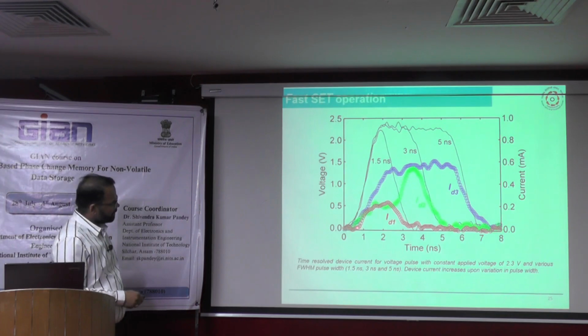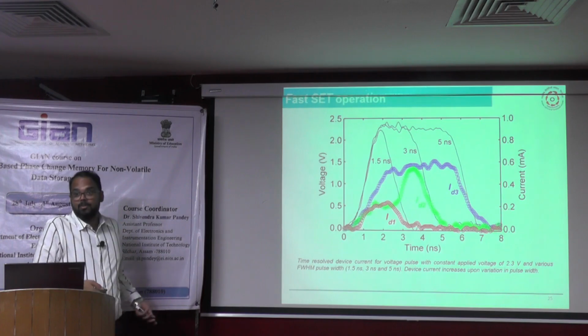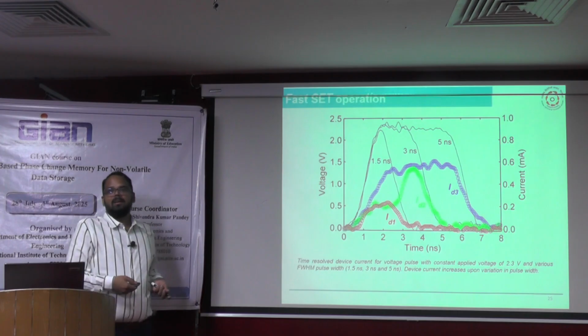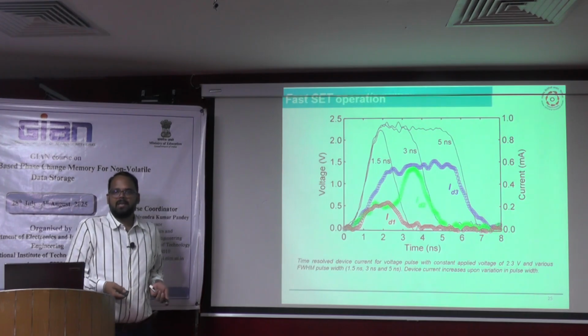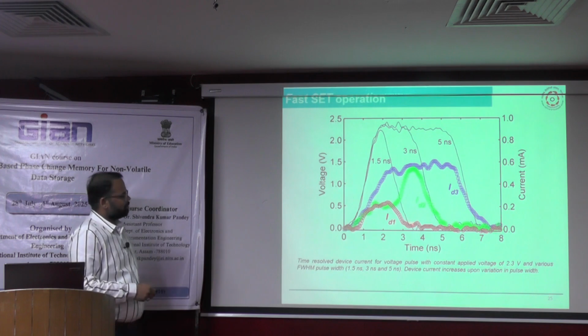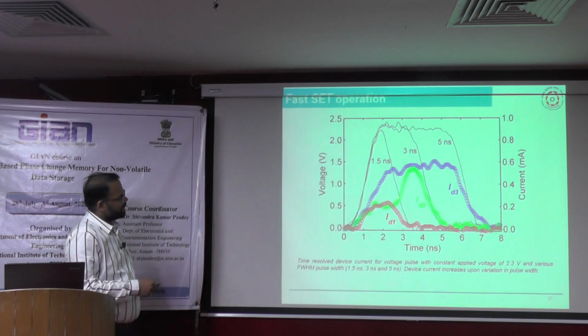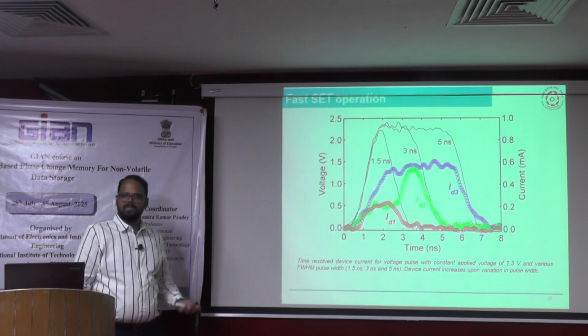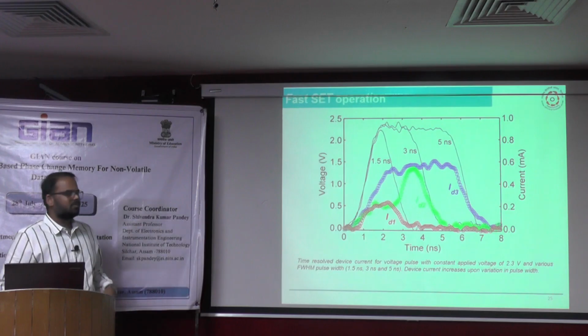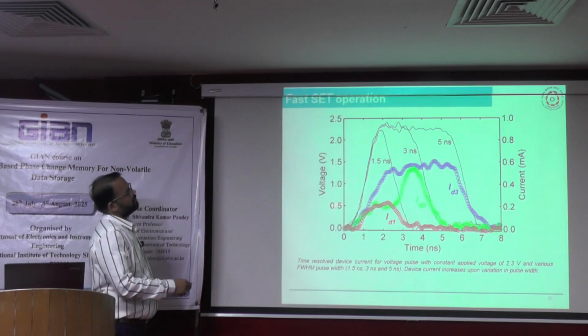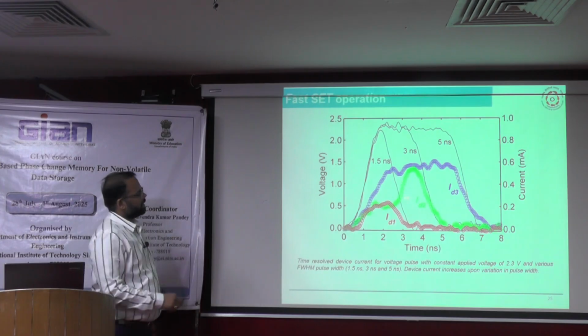Okay. So as you can see, the way we are increasing, the current gets increased and then gets down. But the interesting aspect is that at 3 nanosecond the current has increased and settled down at a particular intermediate state. You can do more study on that, because we have not done any in situ characterization to see what exactly happened here. Then after that again the current value is getting increased, and then it is getting settled down. So we can see what's happening inside this material in that fast time scale, with a fast voltage pulse, and it is changing the current.